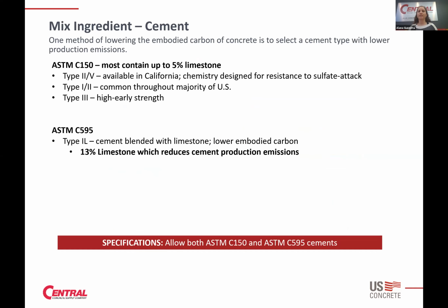And one thing is looking at the type of cement that you're using. And so Michael talked about this, that they are currently using a type 1L cement. And what that means is it's coming from a different ASTM standard. A lot of the cement that's more common that we're used to is an ASTM C150 cement. Different parts of the country will use different types. Specifically in California, we're using a type 5 cement. And so that's one where the chemistry is such so that it can be more resistant to sulfate attack.